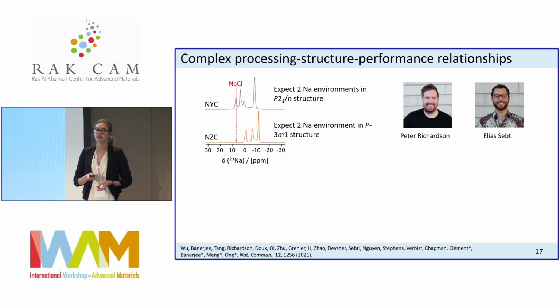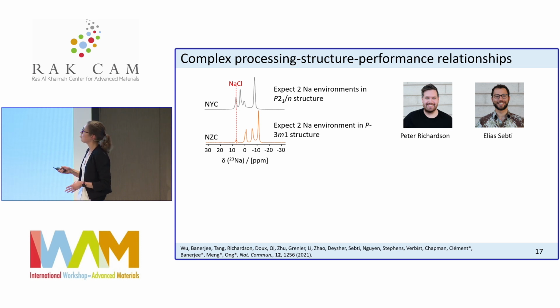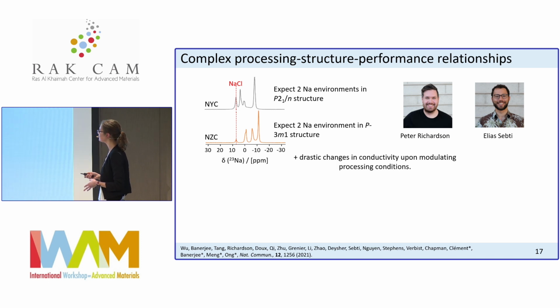The one thing we couldn't answer in this particular study, and this is the contribution from my group here, my postdoc Pete and Elias worked on the sodium NMR of the whole series of systems. I'm just showing you the N members here. What we really couldn't figure out was the structure. So XRD told us that NYC, the yttrium version, was crystallizing in this monoclinic structure where we would expect 2 sodium sites. But in fact, from NMR, we're seeing a lot more environments. On the NZC side of things, we were expecting, again, 2 sodium environments, and we see a lot more signals in our NMR data, suggesting that we haven't quite figured out what the crystal structure is like.